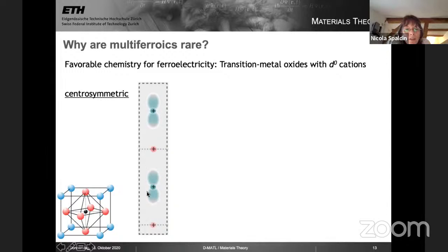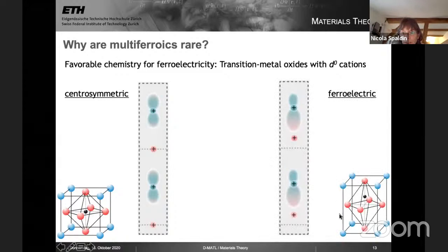So here's my oxygen ion, which has a positive ion core, and the 2p orbital is filled with electrons, and it's centrosymmetric. It's halfway between the titanium 4+ ions that don't have any valence electrons. They're empty shell ions. This is a cartoon of the electron density in the centrosymmetric state. As the temperature is lowered and barium titanate reaches its Curie temperature, it has a structural distortion into the ferroelectric state, and it becomes lower energy for the titanium atom to move away from the center of the two oxygens. This energy lowering is what makes barium titanate a ferroelectric. This is the structure, a bit exaggerated. The titanium moves towards one of the oxygens. There's a structural distortion associated with that, and there's an electric dipole.